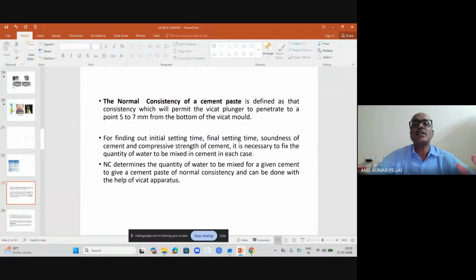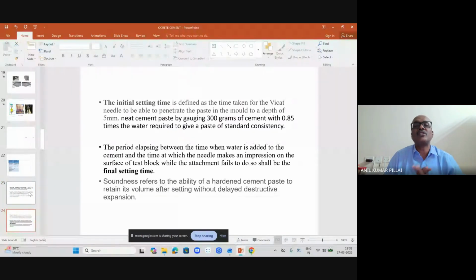So this is what you will find: when the Vicat plunger is allowed to penetrate to a point of 5 to 7 mm from the bottom of the Vicat mold, that is what the NC is actually determined by, and it determines the quantity of water to be mixed for a given cement to give a cement paste of normal consistency, and can be done with the help of Vicat apparatus. And Vicat apparatus can be used to determine the initial and final setting time also.